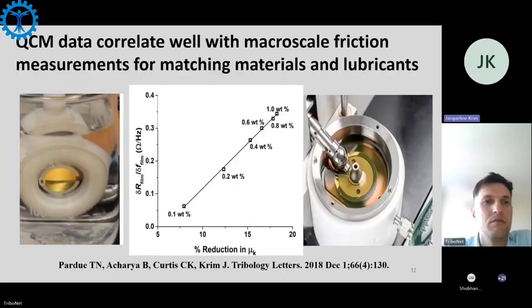We tried this out with the macroscale tribometer for some uncharged particles. These were iron oxide with steric coatings. So the gauge of how much the quality factor goes up with percent nanoparticle added was proportional to how much the friction was reduced in a macroscale system of the same materials.